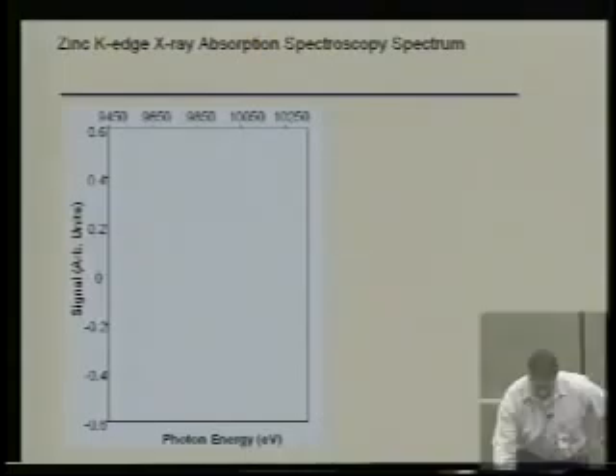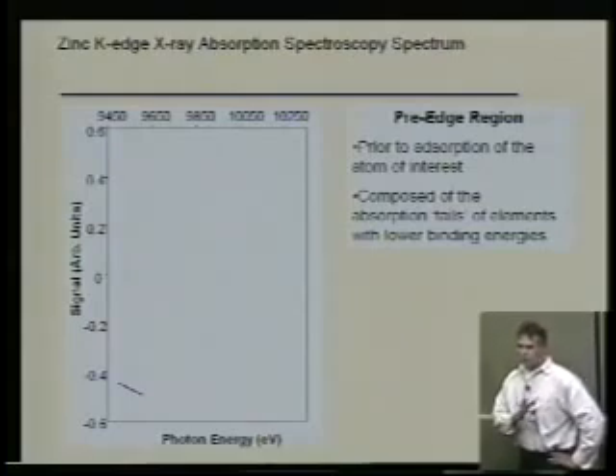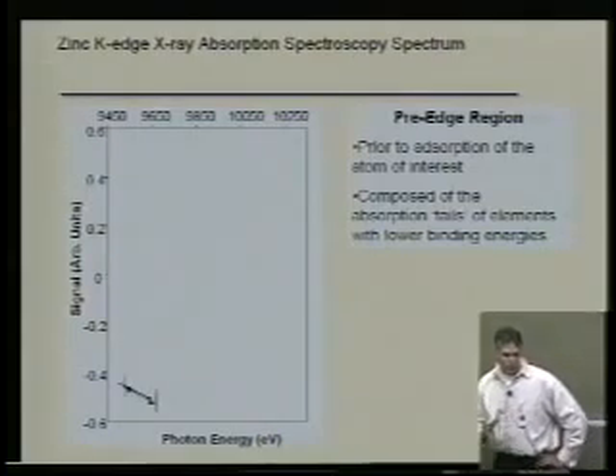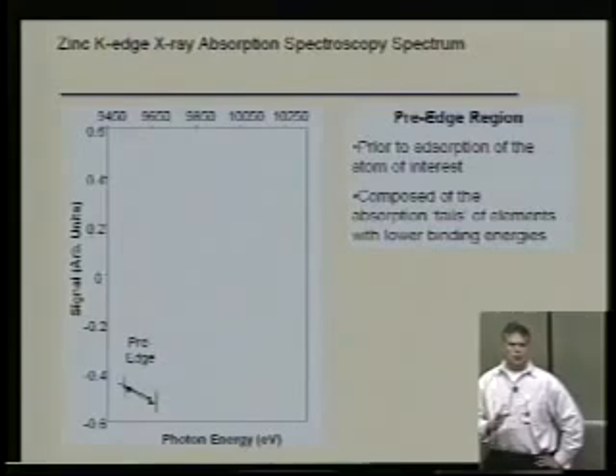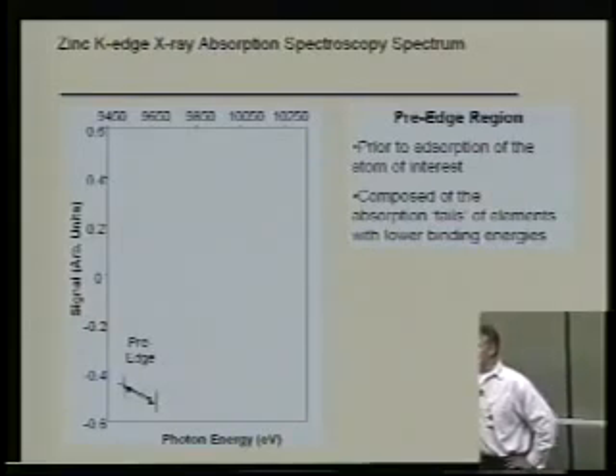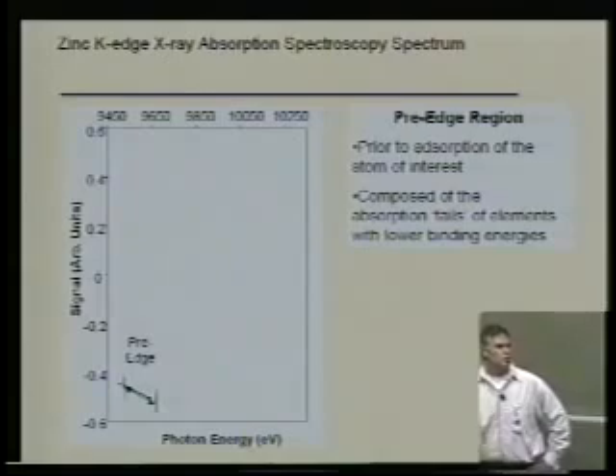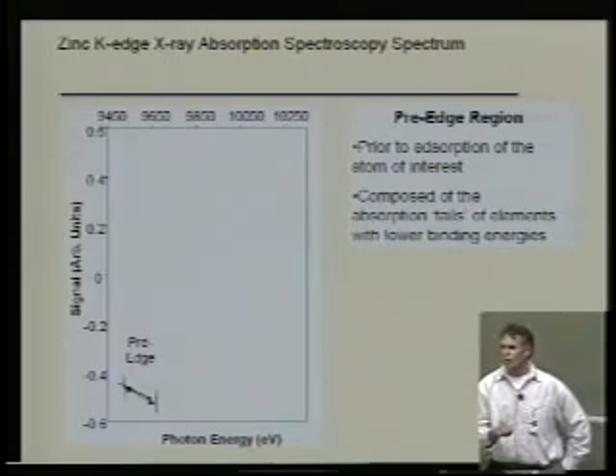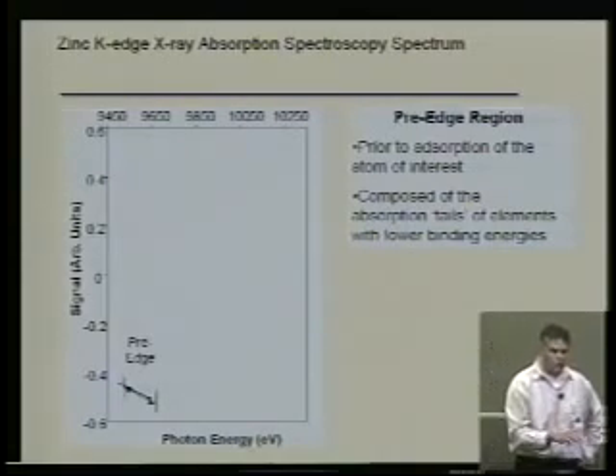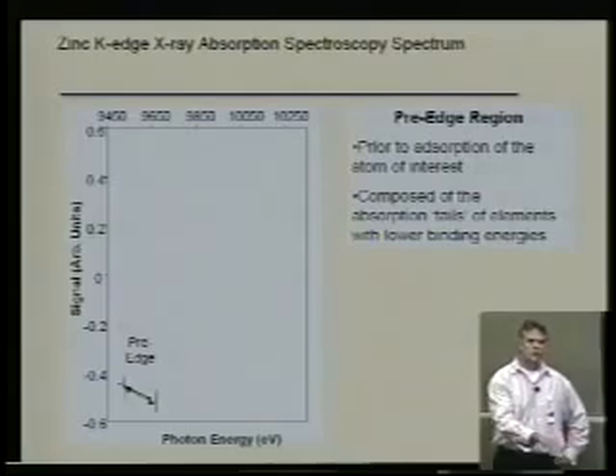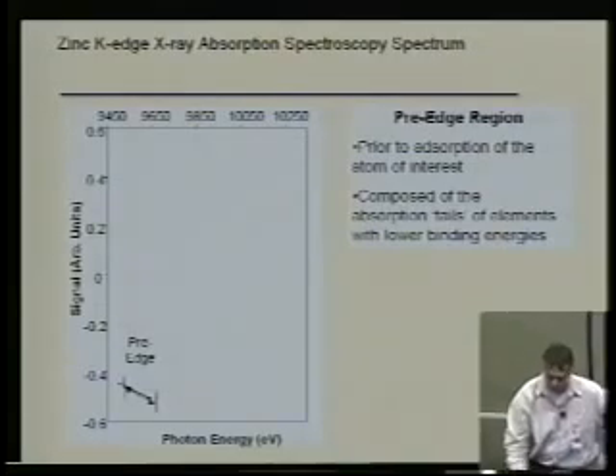So I just want to show you, if you're actually taking a measurement, what does the process look like? This is the zinc K-edge X-ray absorption, and this is at around 9.5 kiloelectronvolts. You start scanning your photon energy, and you have the pre-edge region. This pre-edge region can be just flat, but you can have other transitions, excitations that are lower. So you could have a background there, especially if you're doing these things in electron yield. So it's composed of absorption edge tails that are further down in energy.